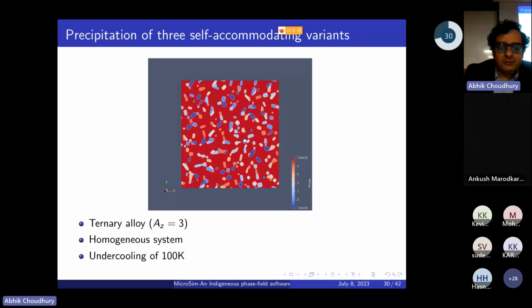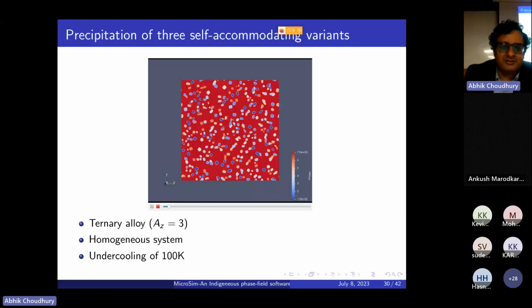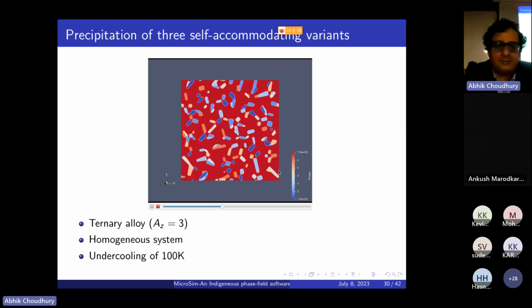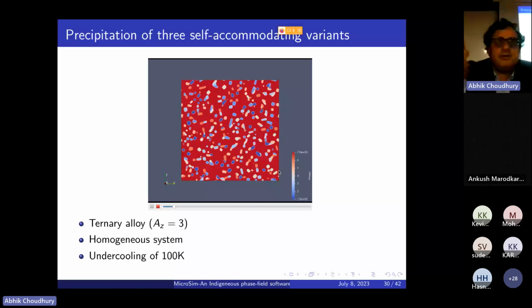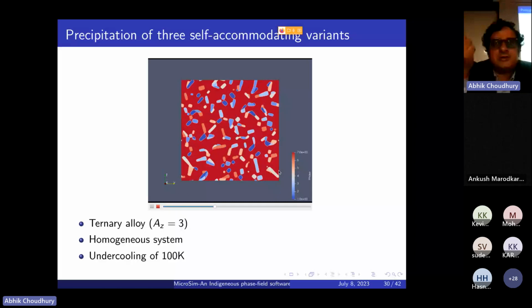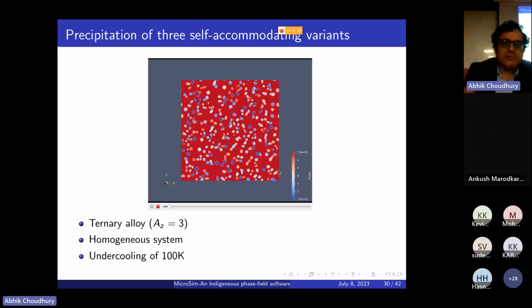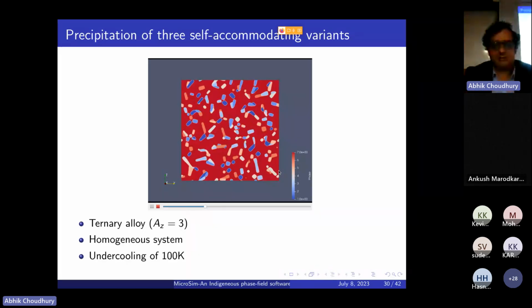And then you can take it even more complicated and include the case of self-accommodating variants, where the sum of the eigenstrains of these variants will add up to 0, and you can include any number of variants and phases, including translation variants, for example, giving you more interesting structure formation in the presence of elastic stresses. This makes it now very powerful, because now the software can do both solidification problems and the corresponding precipitation reactions, which would happen during the post-processing of the material during heat treatment and homogenization. So the entire process chain that is typically relevant for the metallurgical industry becomes accessible to the software.